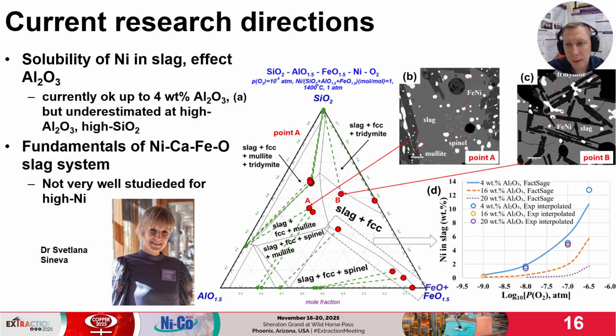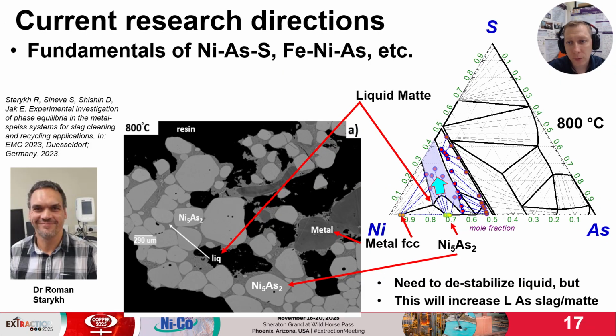Another recent study is the effect of Al2O3 on the solubility of nickel in slag. The model predicts well up to 4% aluminium, but then underestimates when we move into high alumina, high SiO2 region. Also, an important direction is fundamental studies in arsenic-containing systems. These are not very well investigated in the literature. We achieved significant improvements in the database, but there are some challenges to push accuracy even higher. For instance, in this diagram, if we try to destabilize the liquid, we also compromise the distribution coefficient of arsenic